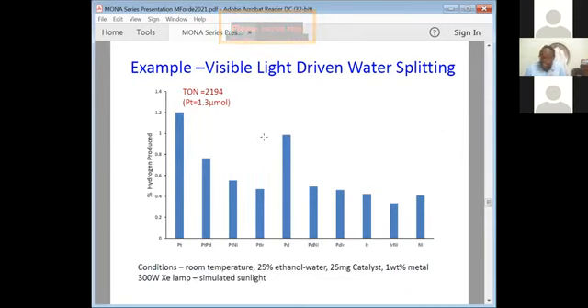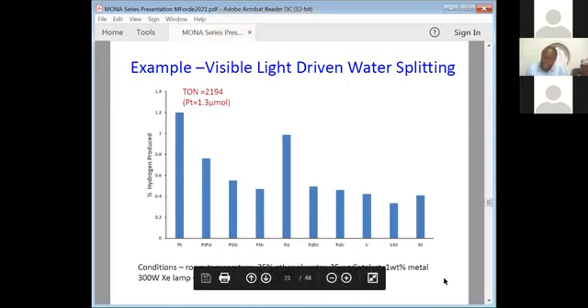Now this, if you compare to literature, under the conditions that we use, is extremely high conversion rates of the photons going to make hydrogen gas. And of course, if we're doing this in a reactor at room temperature with water, the scavenger is ethanol, with a very small amount, 25 milligrams of a 1 weight % catalyst, it's a good basis for us to do our reactions, our biomass conversion reactions at the same time. So that's what we're doing now.